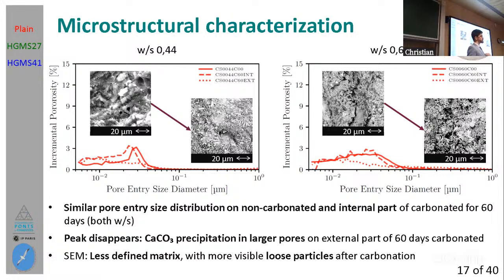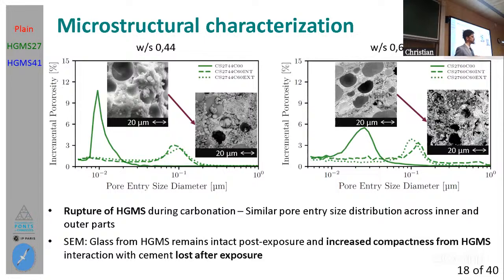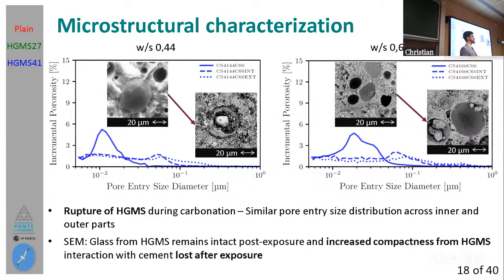If we compare these results to the results obtained for the cement paste with the spheres, we will see something like this. What is interesting about that is that the results of the dashed and the dotted, meaning both the internal and the external part of the carbonated specimens, are roughly the same, which corresponds to a homogeneous carbonation throughout the whole specimen. This was also seen in the cement paste with hollow glass microspheres 41 in spite of the higher strength. So both of these are indicative of rupture that is occurring in the spheres throughout the carbonation exposure with 20 megapascals. And what is also indicative of that is that we are having some loose particles of calcium carbonate that have precipitated already inside the spheres.